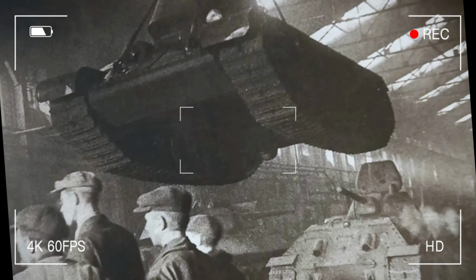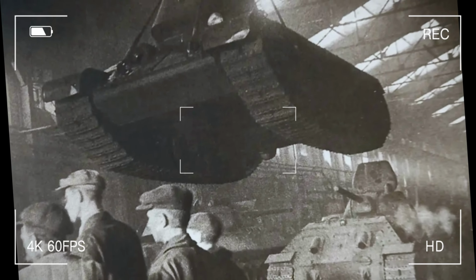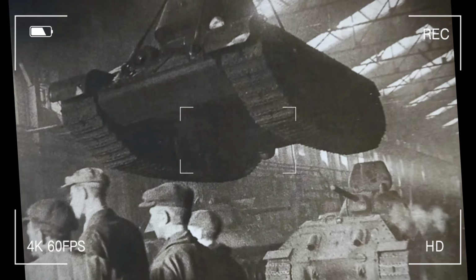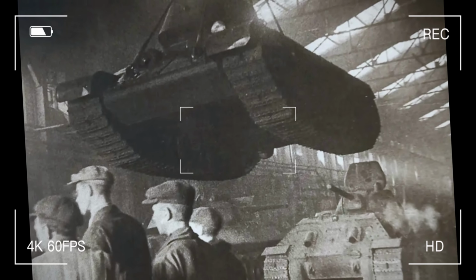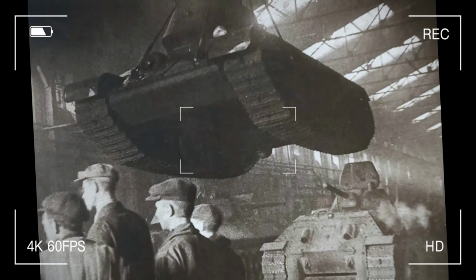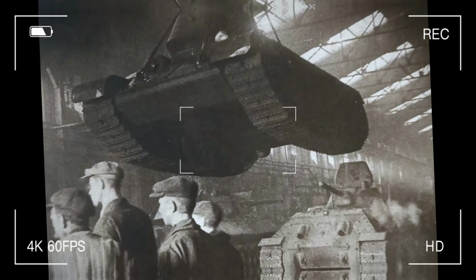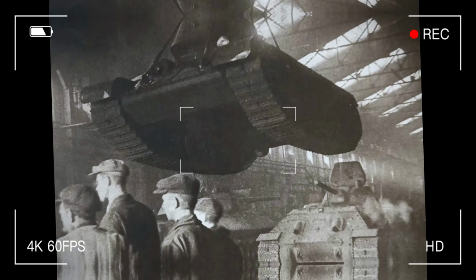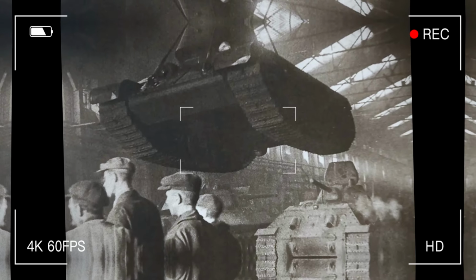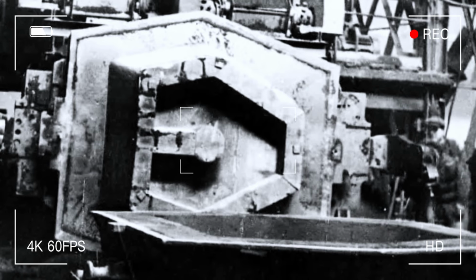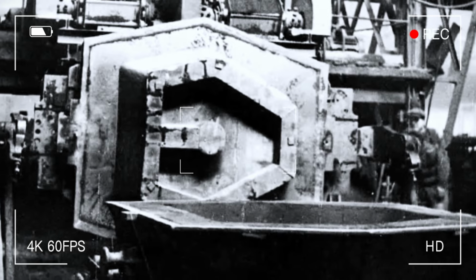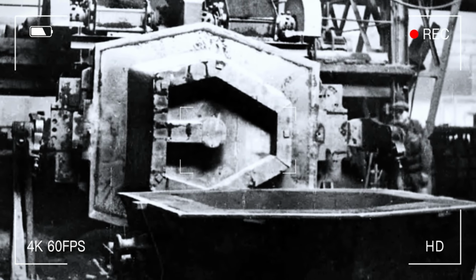Track 4 to 6 different melt batches, with at least 4 turrets cast from each. But reality, as usual, had other ideas. In the end, the researchers kept a close watch on 29 turrets made from steel grade 8S and 58 made from steel 44L. That's a colossal amount of data to process by hand in 1943.